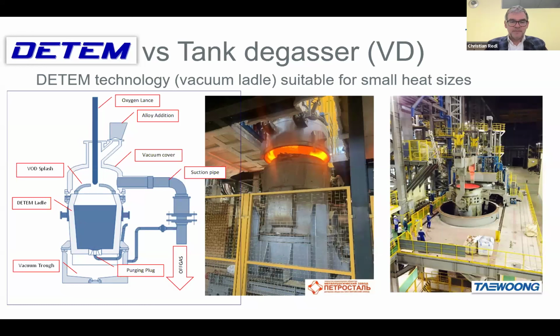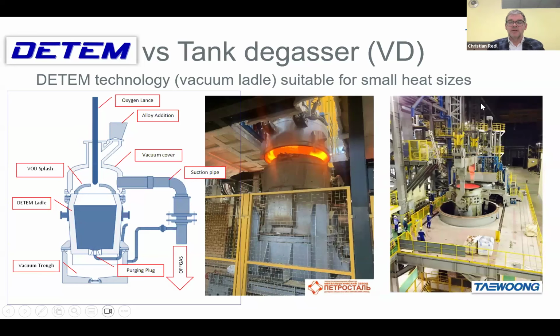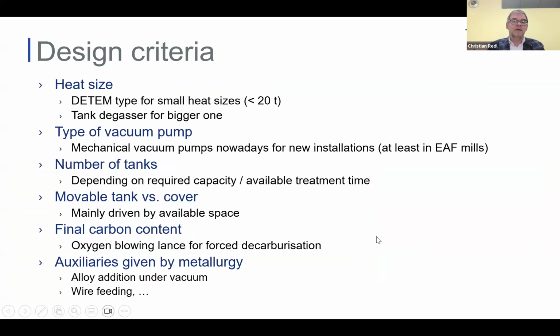The typical installation in a special steel plant is nevertheless the ladle tank degasser, where you place the ladle in a vacuum tank and seal the entire vacuum tank by a ladle cover, which is shown on the right side. Here we are showing a typical installation for a heat size of 120 to 150 tons installed in a steel plant in Korea. Of course, there are many different design types of this tank degasser, so I will review a few of them. One is the heat size. At Indeco, we recommend this DETEM type vacuum ladle for small heat sizes, smaller than 20 tons, and the tank degasser for the bigger ones.